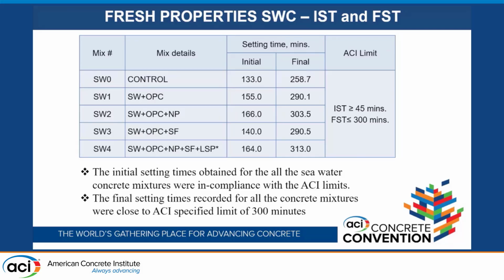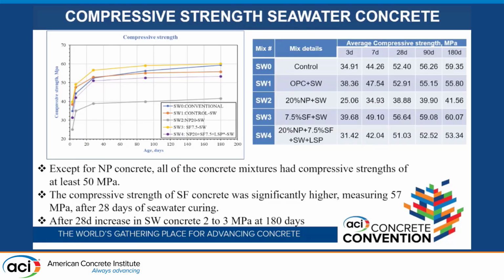We then looked at the initial and the final setting time, and the initial and final setting times obtained for all of the seawater concrete mixes were in compliance with the ACI limits, and the final setting time recorded for all the concrete mixes was close to the ACI specified limit of 300 minutes. Some of them were like 258.7 and 290.1.